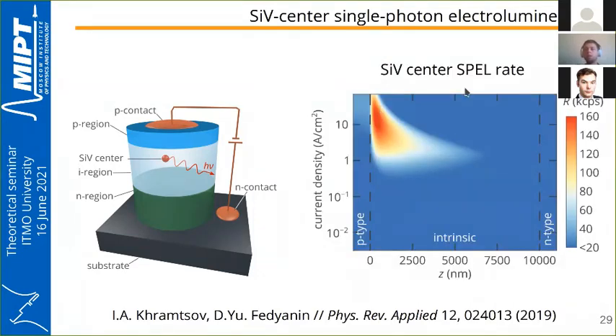It can be seen that the SiV center, and actually any other color centers, should be located at a distance of 200 to 500 nanometers from the PIN interface. Also, there are current regimes that should satisfy our device in order to obtain high brightness from the color center under electrical pumping.